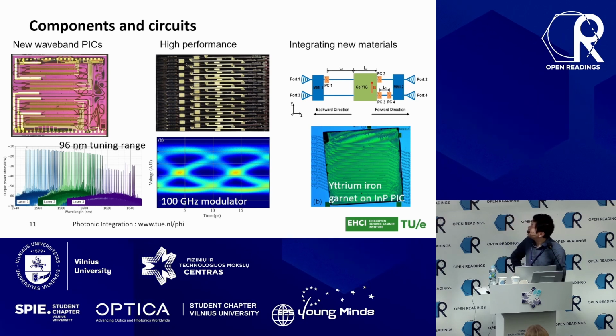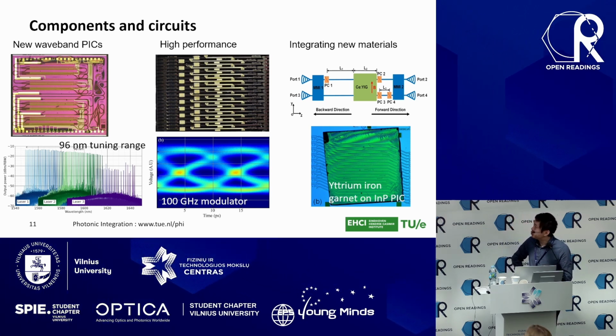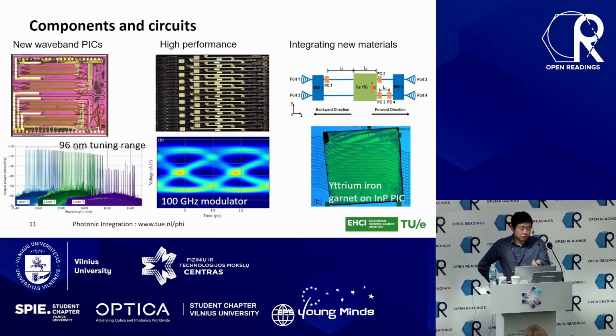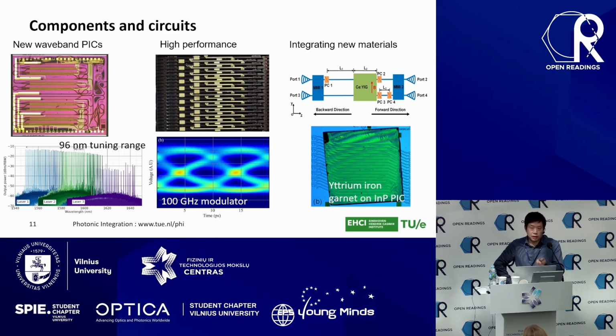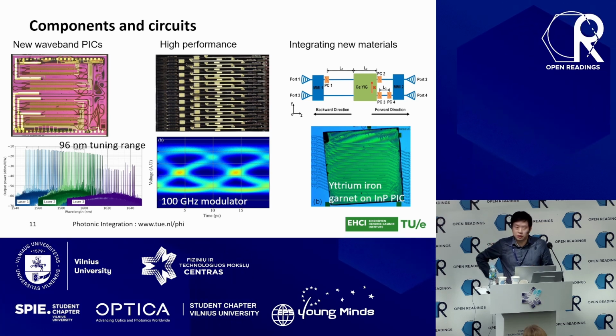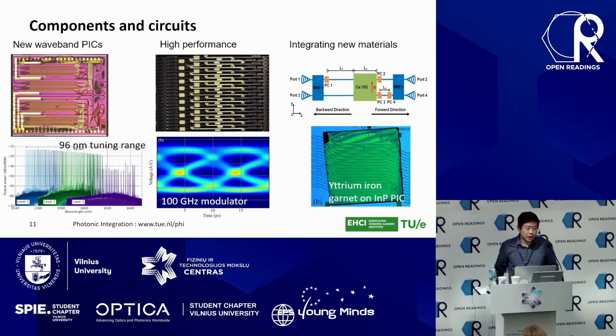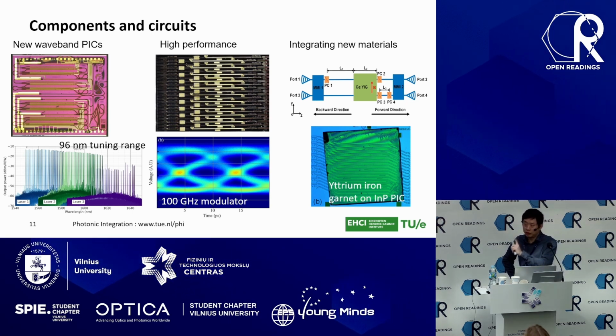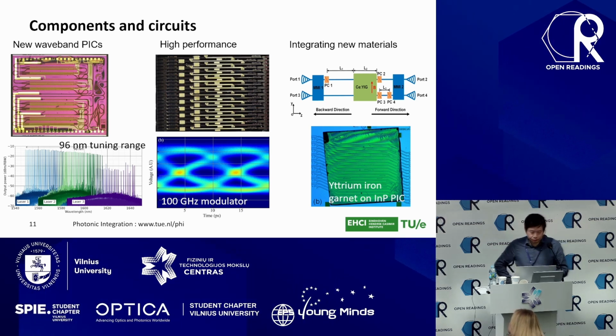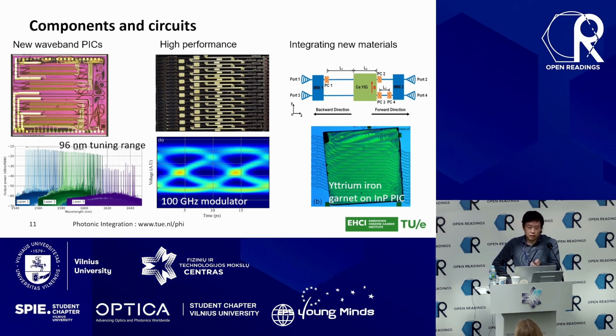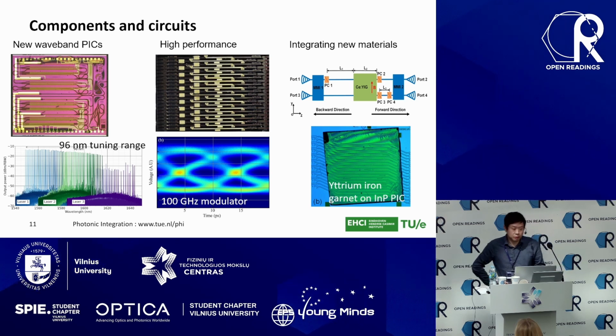Just a few examples of the recent new chips that we have made. This is a recent laser chip that we developed, which is a tunable laser, completely integrated in a 5 by 5 square millimeter chip size, and it can achieve about 100 nanometer continuous tuning. So it was one of the records. And in the middle, you see a highly densely integrated optical modulator, which can be modulated beyond 100 gigahertz. And we are also trying to integrate new materials, like, as you can see here, a cerium doped yttrium iron garnet material, which is a magneto-optic material, onto our waveguide, so we can actually create optical isolators on chip.